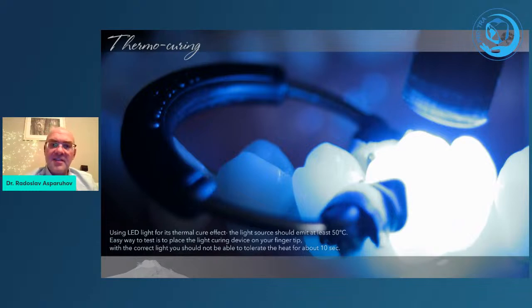So in those cases, the light curing device should emit at least 50 degrees Celsius of heat. Then the material is going to set faster and it's going to become stronger. And we will save a little bit of time. It is important to underline that this heat curing or thermal curing should be done while the material is still setting. This is not the light curing stage with the coating, resin coating. This is done while the material is still setting.